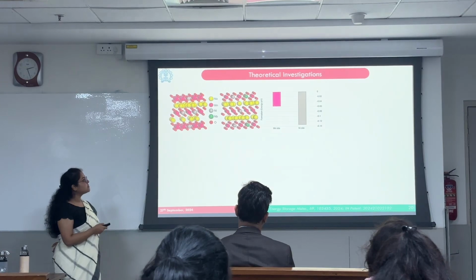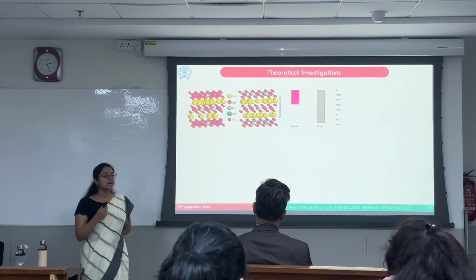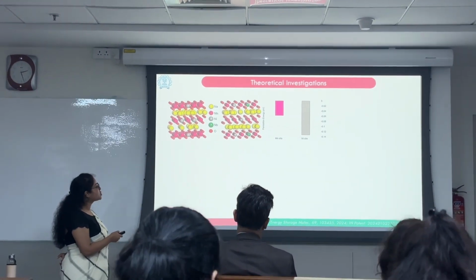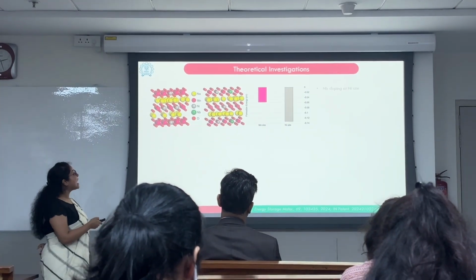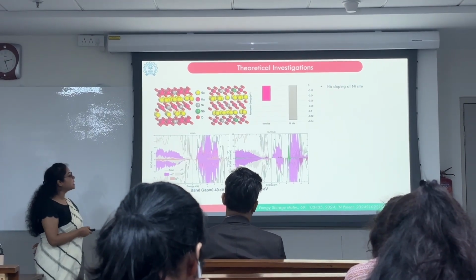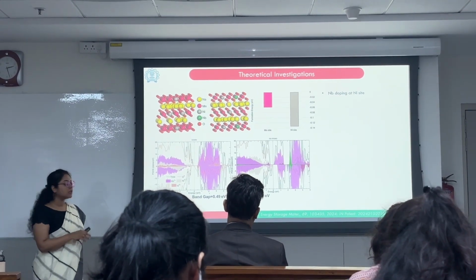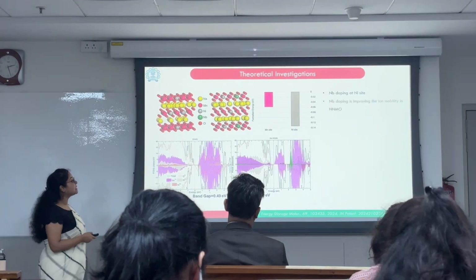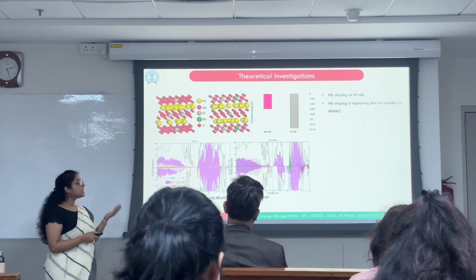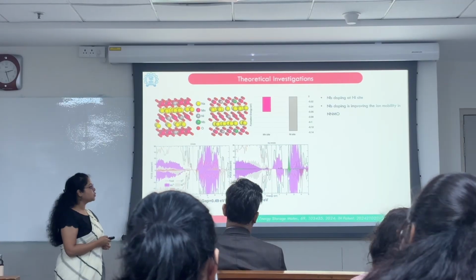So the theoretical investigation started by identifying where does niobium get stored, which is at the nickel site. And through the PDOS calculation, we observed that there has been a lowering of the band gap, which suggests that it has a better ionic mobility in comparison to that of the pristine one.